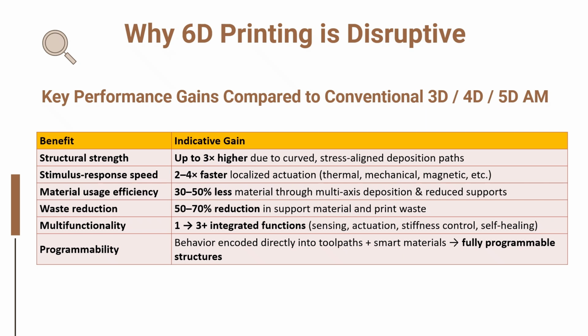First, structural strength can increase by up to a factor of 3. This comes from curved, stress-aligning toolpaths that follow real load trajectories, something traditional planar printing cannot achieve. Second, the stimulus responsive speed improves dramatically. Because we can orient material domains in 3D space, actuation becomes 2 to 4 times faster, whether it's thermal, mechanical, electrical, or magnetic. Third, 6D printing is far more material efficient.